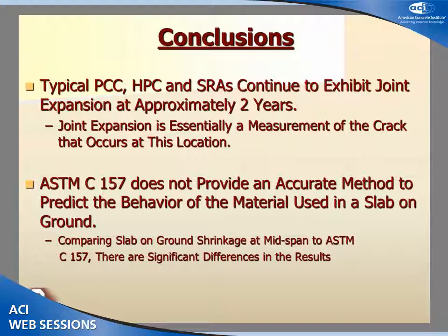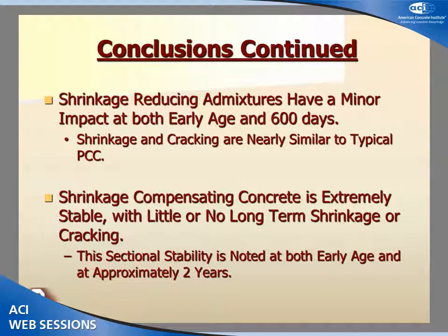We compared the results, and we found there are significant differences between the results. We also found that the shrinkage reducing admixture has a minor impact at both early age and 600 days, and is very close to Portland cement concrete. And finally, we found that the shrinkage-compensating concrete is extremely stable with little or no long-term shrinkage or cracking. This was the result at the early age and also for approximately 2 years.